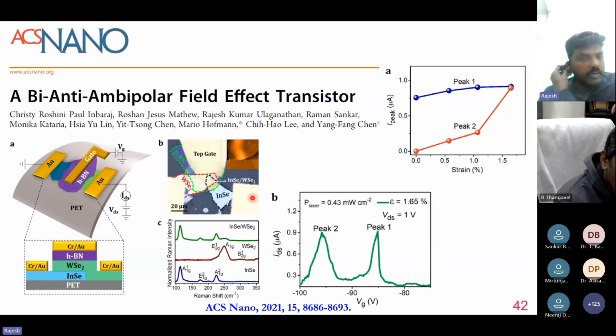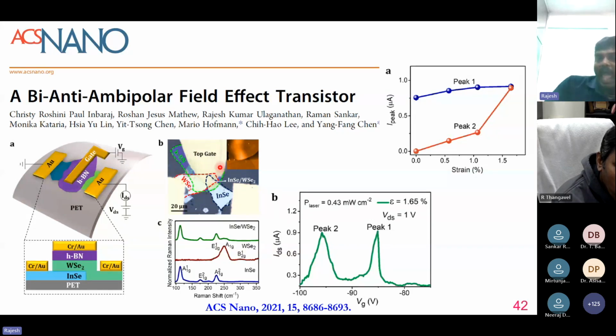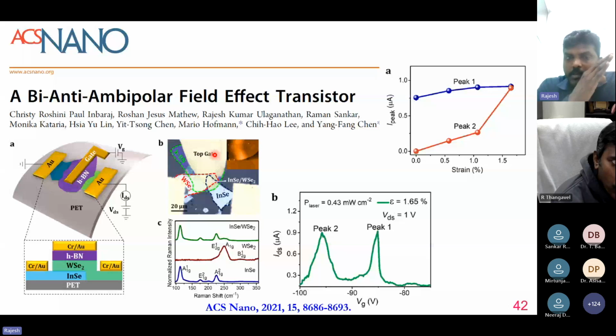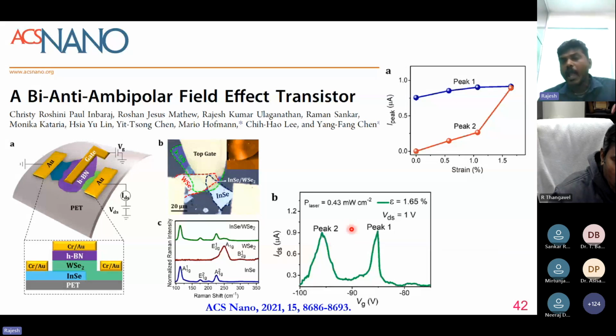In this work, we exfoliated indium selenide and tungsten diselenide, and also placed hexagonal boron nitride, and we fabricated a device. Interestingly, we observed anti-ambipolar behavior. So, what is ambipolar behavior? Ambipolar behavior, as I showed previously, has both P type and N type nature, so it looks like a V kind of structure. But in these studies, we observe an inversion of the V. It's called anti-ambipolar. By creating this kind of structure, we are able to achieve this anti-ambipolar behavior.